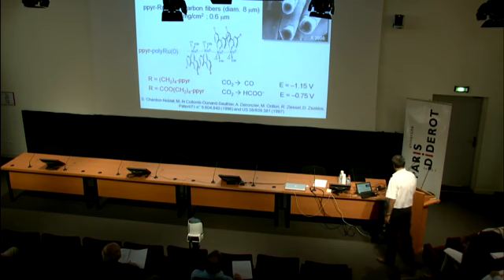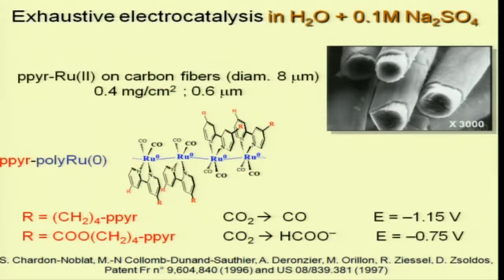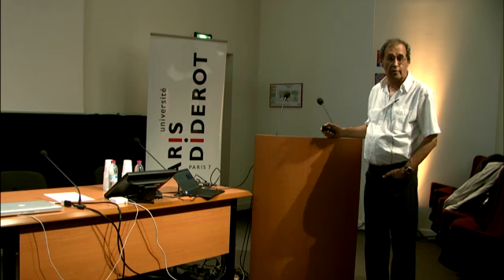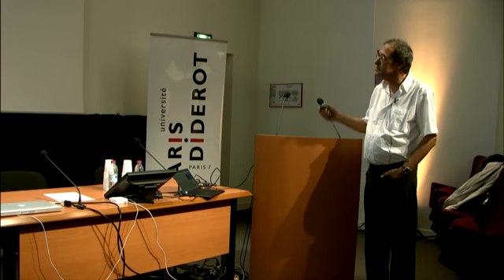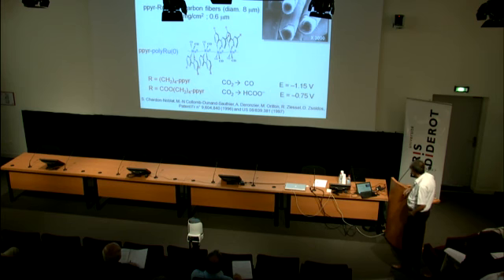So we check that by, of course, the same exhaustive electrocatalysis in water. For instance, at that time we used a carbon microfiber. If we did the job today, we would probably use a carbon nanotube, but you know, it's 15 years ago. So that's the picture of the microfiber. You can see here the typical polypyrrole film on the surface, and you obtain exactly the same selectivity, depending in particular on the substituent of the bipyridine ligands.